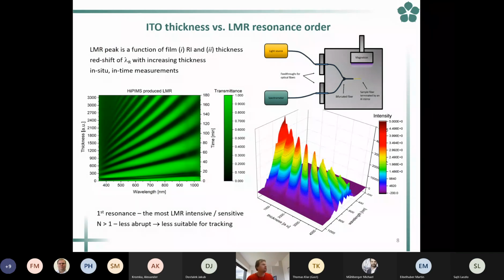That's a little bit more complicated. I don't want to go into more detail, but for the lossy mode resonance, the optical way of detection, we are working with so-called modes of resonance. Here you can see the basic mode and then the higher mode. Actually, you can see them here. And the principle of the detection is that once the optical fiber coated by the film is surrounded by some medium, the refractive index is changed, and these resonance modes are shifting. And from this shift, we are able to